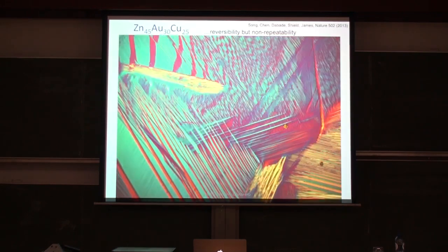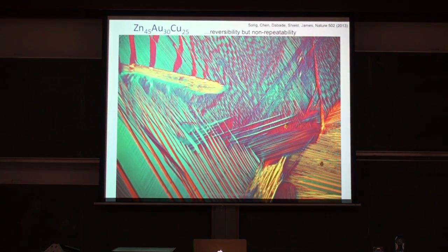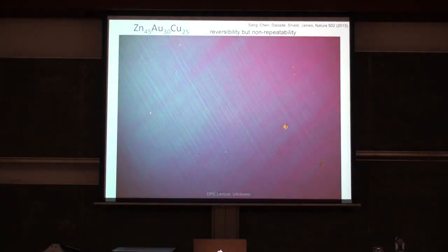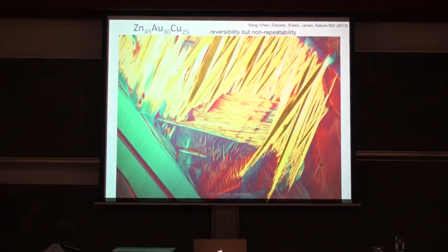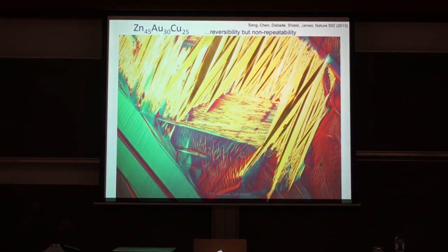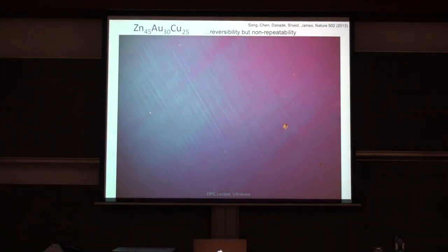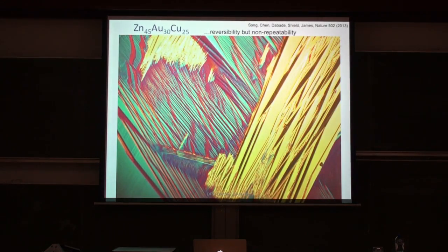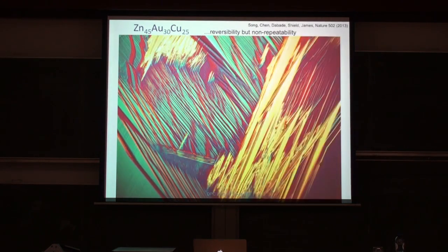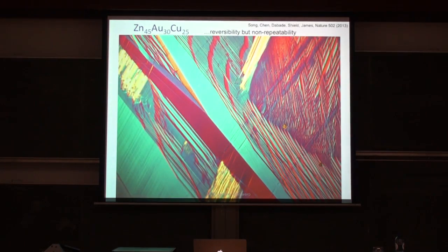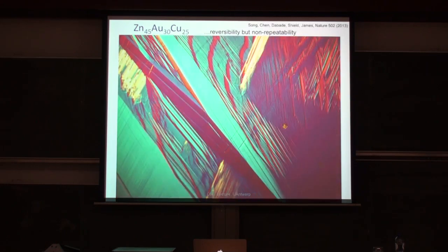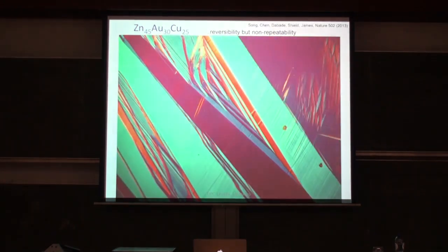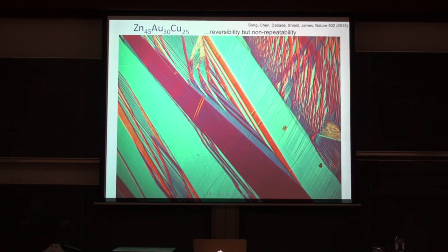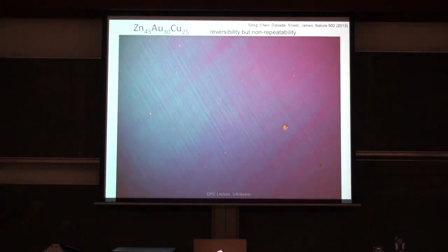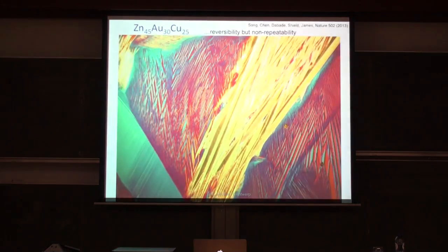And we saw that the transformation temperature was very steady. All the properties, we measured the latent heat, you know, all the typical properties of phase transformation, at least to 20,000, were very steady. But the most interesting thing is, if instead of doing gold 30, whatever, you do gold 28 or gold 27, it's a completely different alloy. I mean, it really depends on satisfying these kind of conditions very closely. The deviations from somehow perfect geometry really matter a tremendous amount.